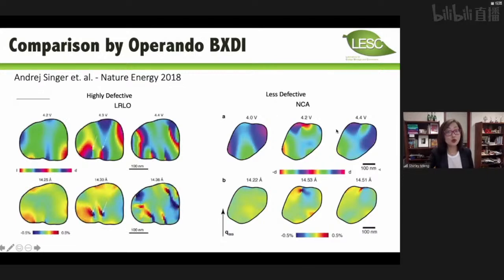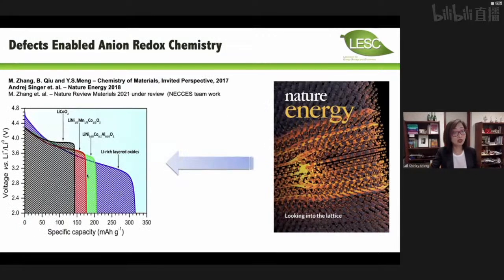So the classical materials and the new anion redox materials have completely different tolerance to the defects. And for material scientists, the question is whether it is a good defect or a bad defect. If you have the defect density engineered correctly in the particle, it can indeed store more lithium and release more lithium reversibly and give you more energy density. So this kind of breakthrough in the energy density for the cathode materials is so exciting for us.